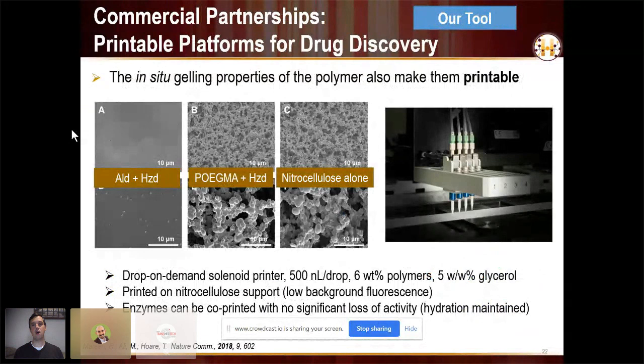So what we did was to try to print these hydrogels onto basically nitrocellulose paper sheets. And the benefit of doing this versus a traditional solution assay is that we can really reduce the volume that we need in order to assess drugs of particular concentrations. So for drugs that are potentially very interesting, but are isolates from bacteria or plants, very hard to get large volumes of them, this can reduce the screening requirements,